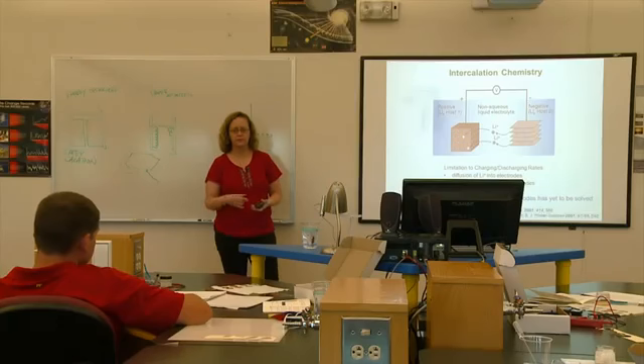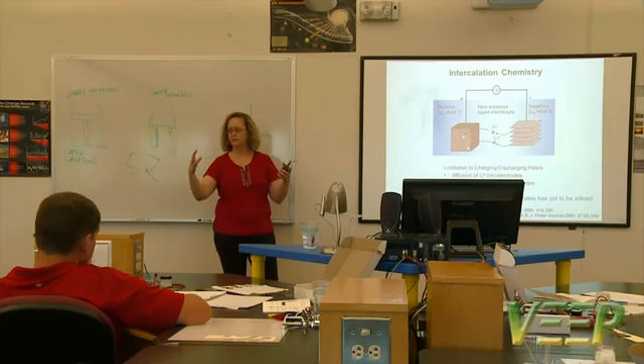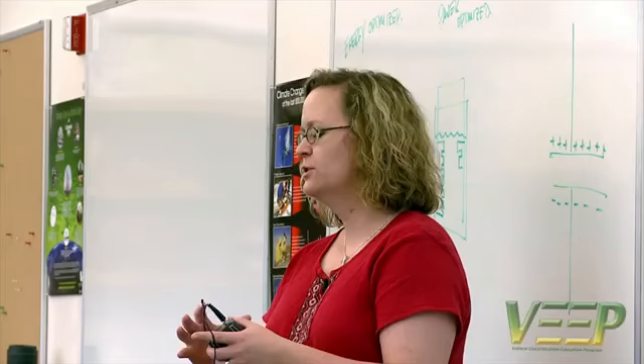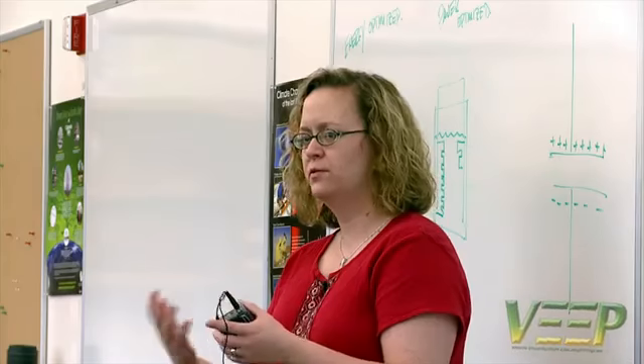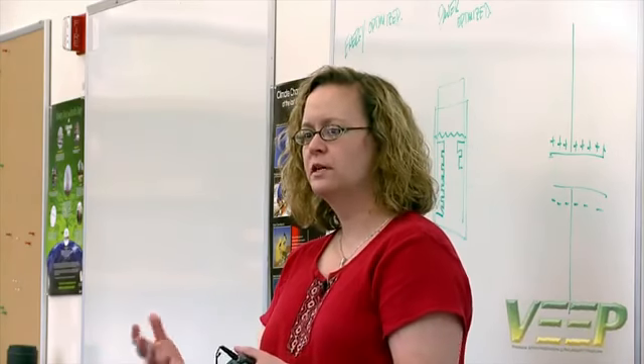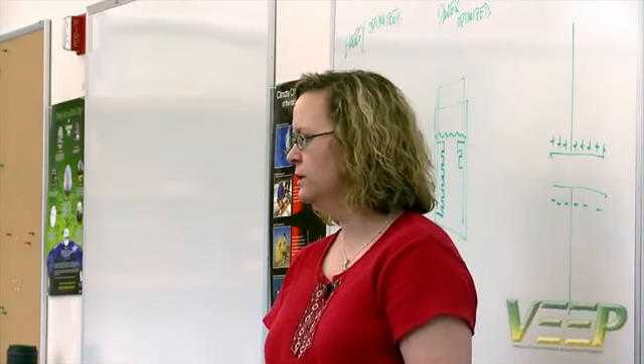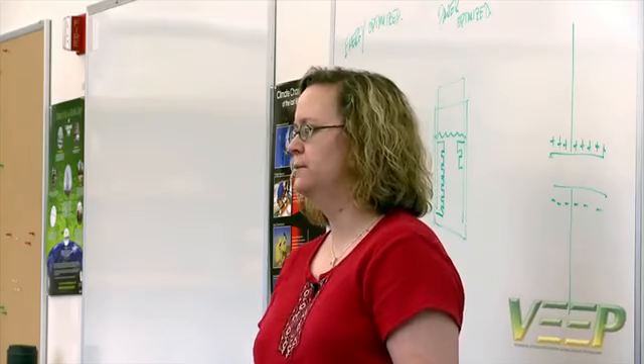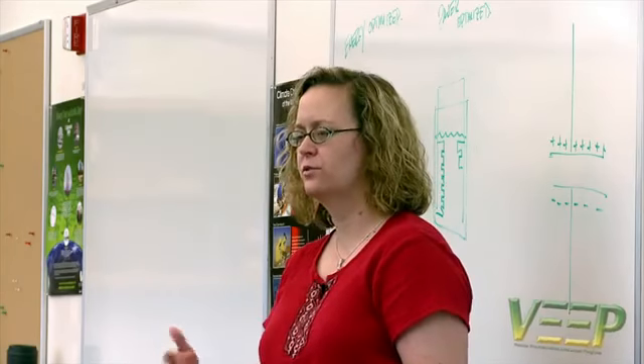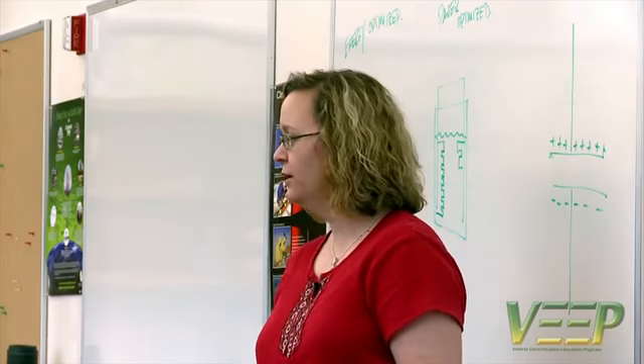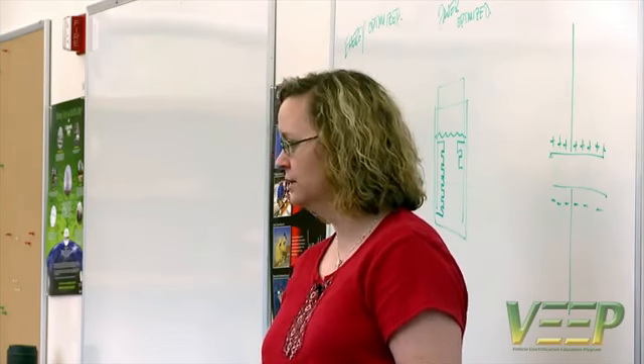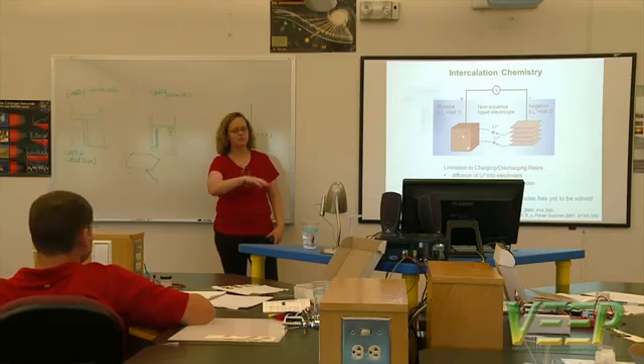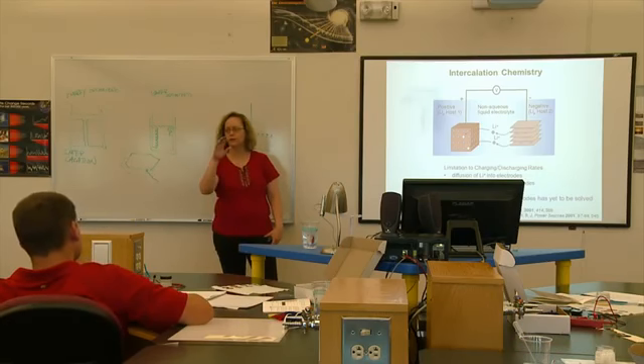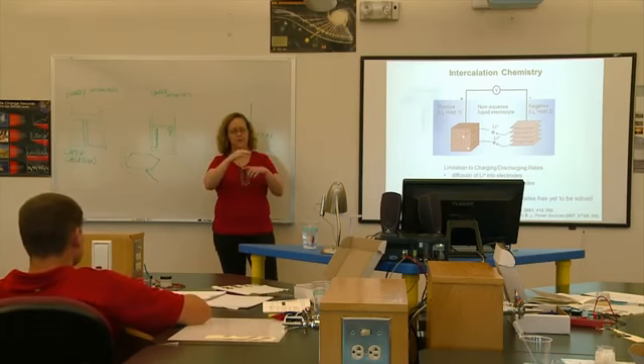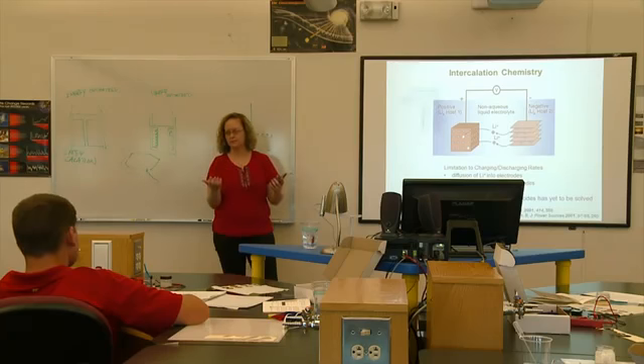So a couple of things happen there. One, you're taking an electrode. Every time you put lithium into it, it has to expand in volume, and every time you take lithium out, it contracts. So over time, your electrodes pulverize themselves. So if you notice that your cell phone is not keeping good charge anymore, there's no chemical degradation that's really happened. It's that your electrodes have pulverized themselves, so they're not in good electrical contact anymore. So you're carrying around all this weight that you're not using. That's part of why batteries are never discharged all the way and charged all the way. If you stay kind of in a narrow range, this volume expansion isn't as bad.